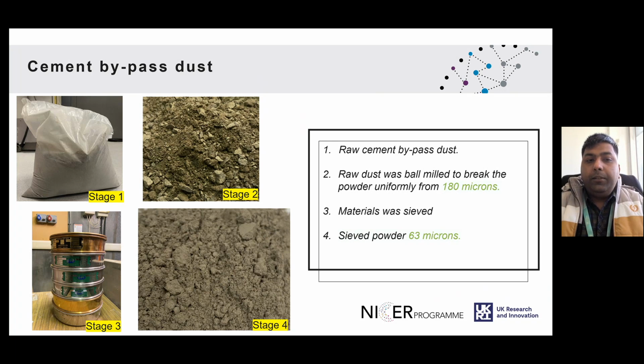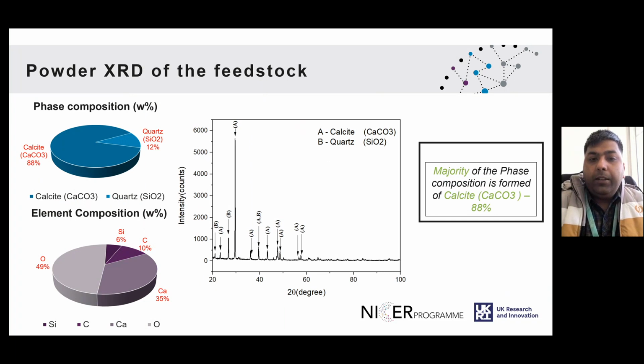So what we have shown here is a sample of the bypass dust that we have collected and gathered from the source, which was then subsequently sieved to prepare a homogeneous powder of a uniform size of 63 microns approximately. After this powder was homogenized and sieved, we have taken it to the material characterization instrument such as X-ray diffraction. And that X-ray diffraction revealed that the cement bypass dust, that raw material that we obtained, was primarily consisting of calcium carbonate and silicon dioxide, as shown here through the labels.